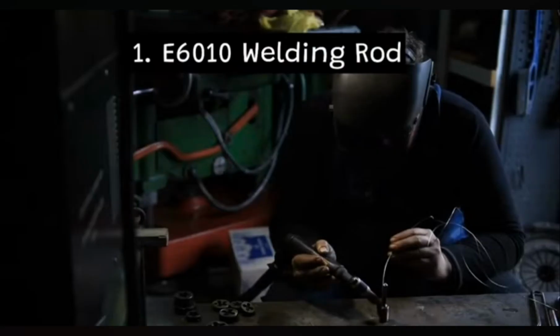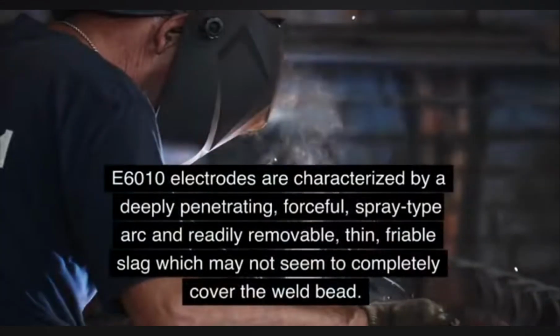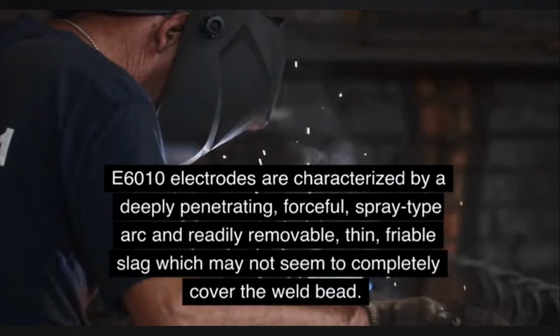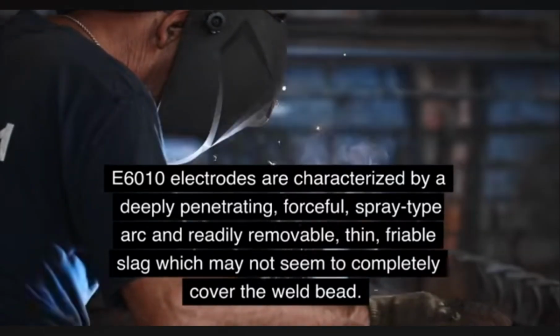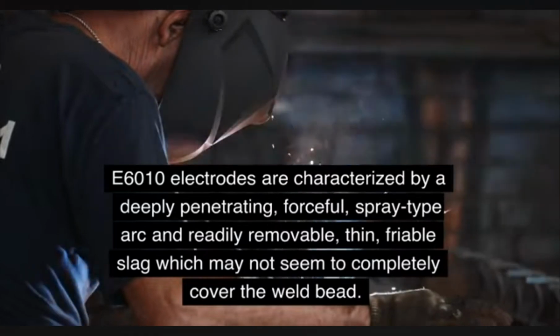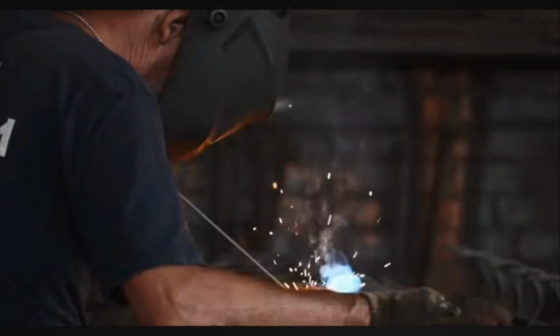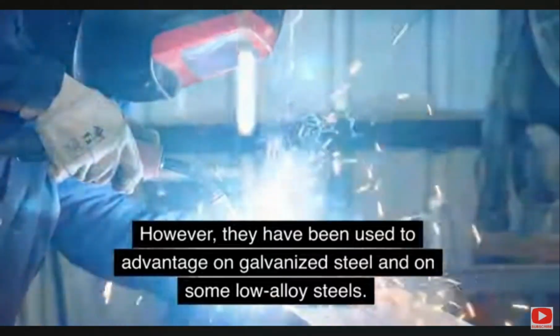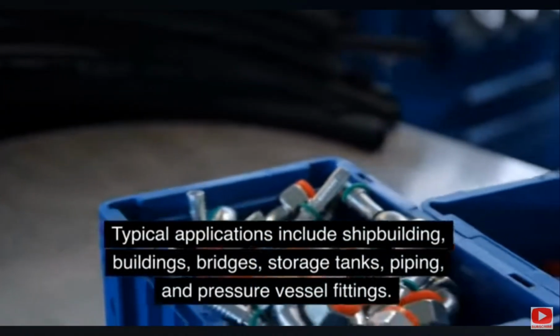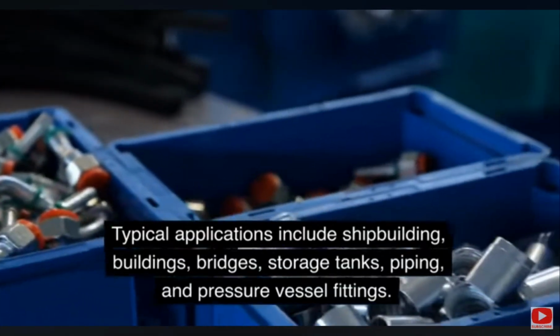Friends, during this session, we discuss welding electrode types and the selection of welding electrodes for getting better welding quality when welding different metal parts. E6010 electrodes are characterized by a deeply penetrating, forceful, spray-type arc and readily removable, thin, friable slag which may not seem to completely cover the weld bead. They have been used to advantage on galvanized steel and on some low-alloy steels. Typical applications include shipbuilding, buildings, bridges, storage tanks, piping, and pressure vessel fittings.